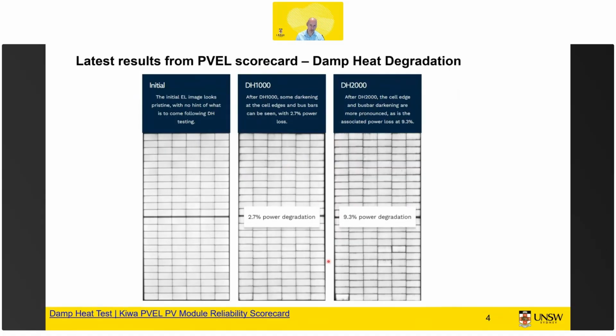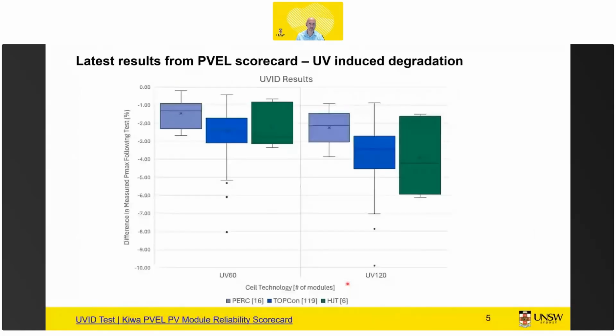They see very similar results as us, that for glass modules, for example, you see degradation coming in at the edges, which is shown here with EL images, electroluminescence images, where bright means good and dark means bad. And you see that the darkness enters from the side, because that's where the water gets in.